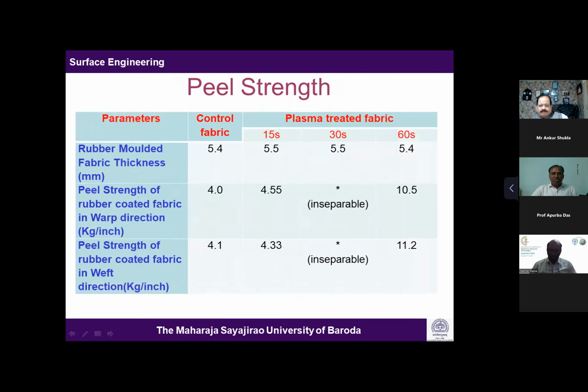The peel strength also shows an increase. It was found that at 30 seconds, even the peeling was difficult. It could not be peeled. So there is a notable increase in the peel strength. This shows that the binding between the matrix and the reinforcement is improved because of the surface roughness.